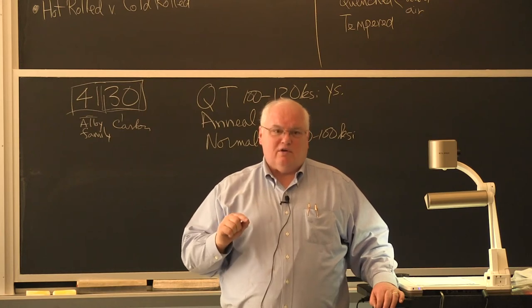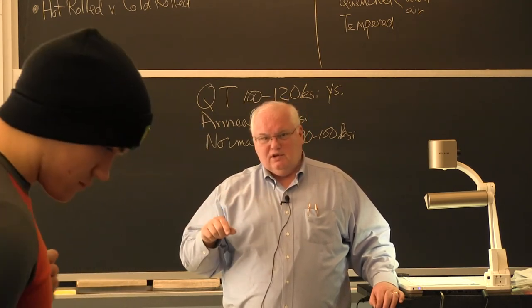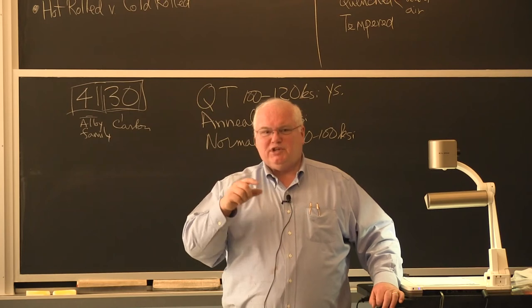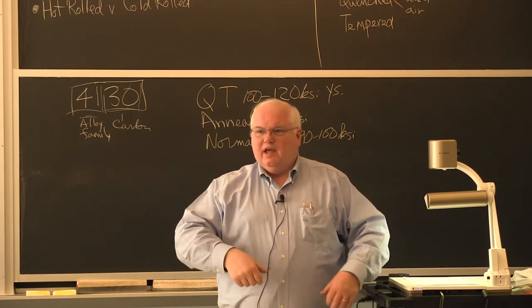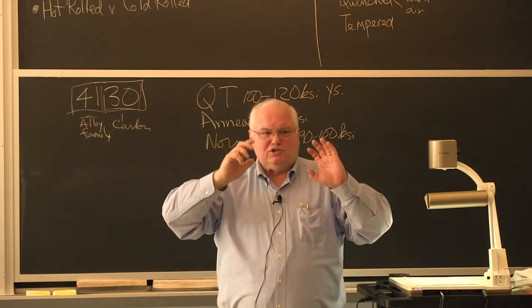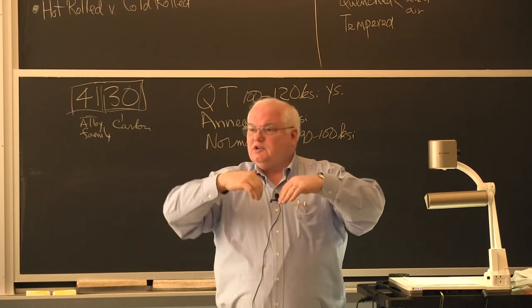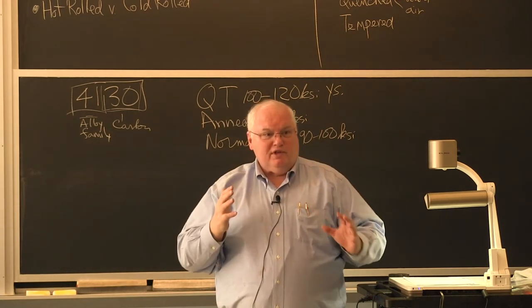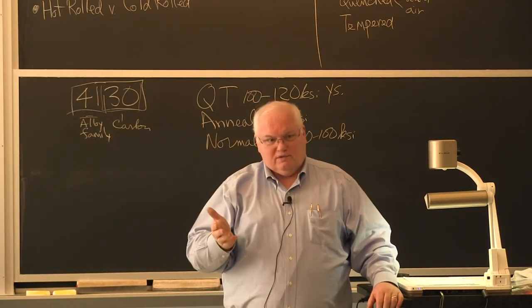And it started a crack and it grew by fatigue until it was like 60% of the way around. And on one jump, the thing just broke. But the final failure was nice and ductile, the steel bent over and everything. Well, unfortunately, the first part wasn't.